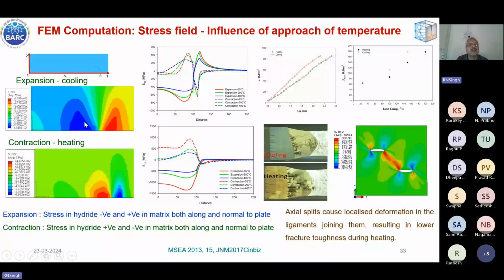We see that inside the hydride we have compressive stresses, and just outside, we have tensile stress in the matrix. However, when you heat the same sample and dissolve it back, what you get is surprising. Now, inside the tip of the hydride you have a tensile stress, and in the matrix just outside, the stress has been reduced. These calculations were done at various temperatures. The dotted line shows the contraction lines, and the solid line shows the expansion line.